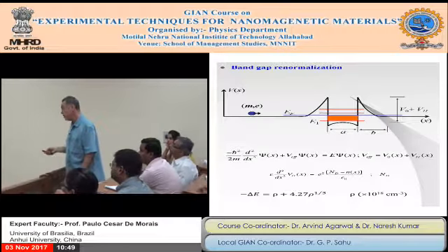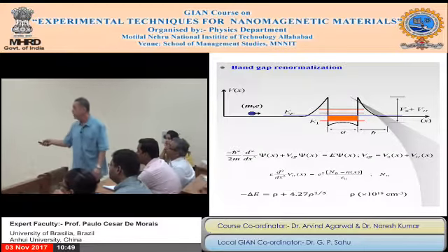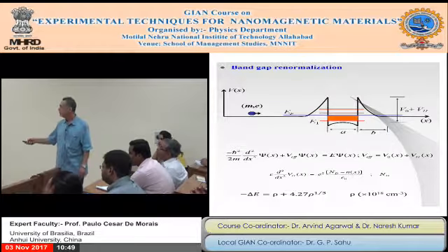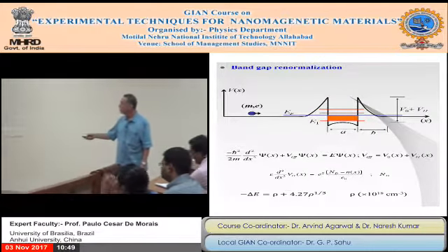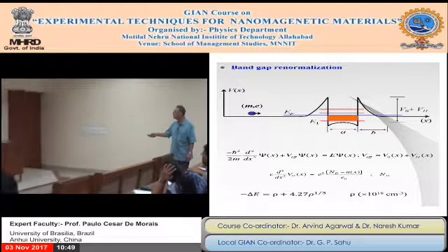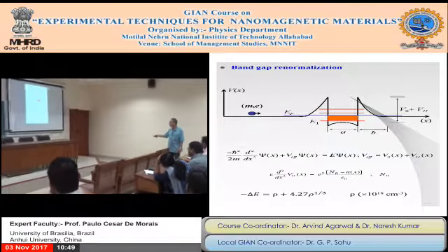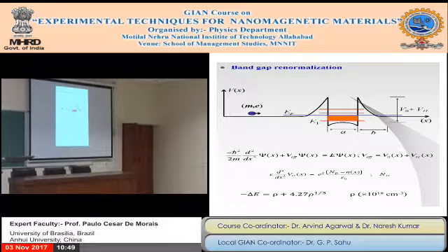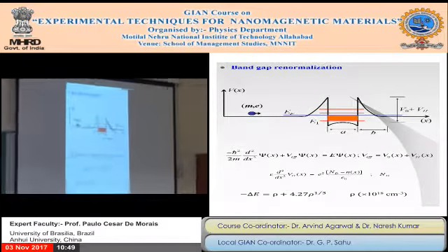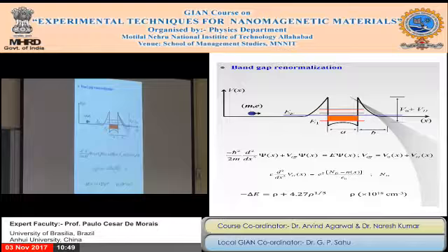Okay, once we have this in mind, here again is the Schrödinger equation, the same. Only here you have the effective potential, and the effective potential now is the initial potential plus some extra potential. This extra potential is called the renormalization potential, and it comes from the band bending and band gap renormalization.